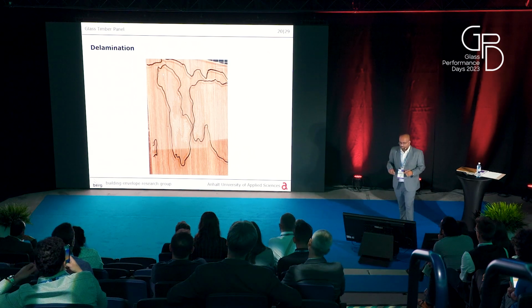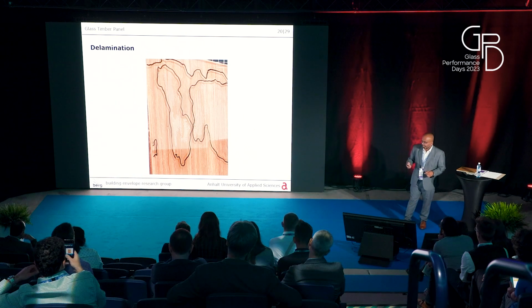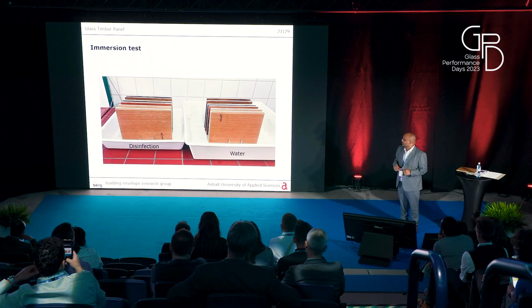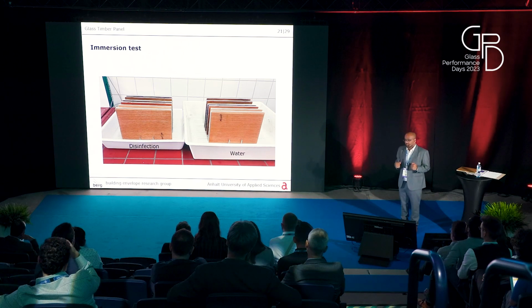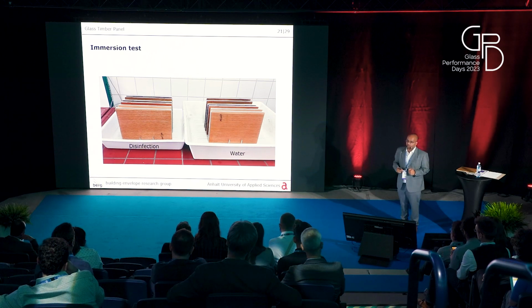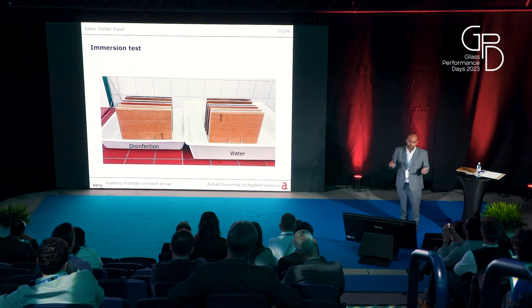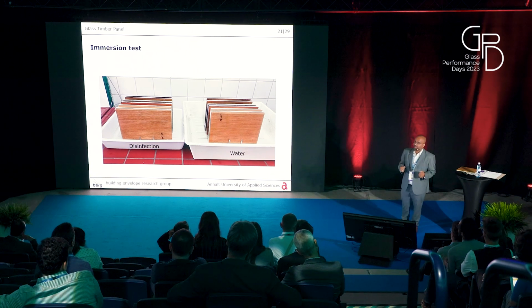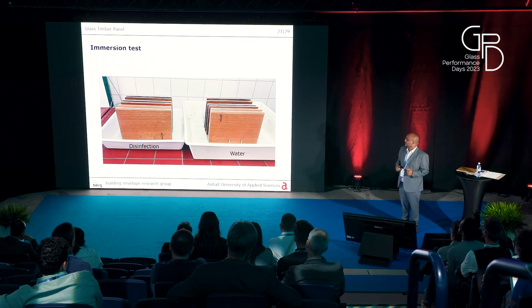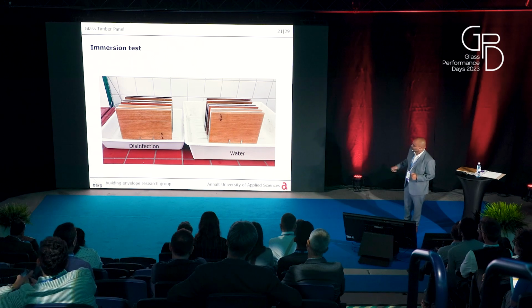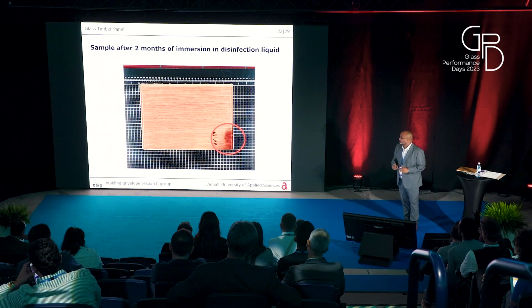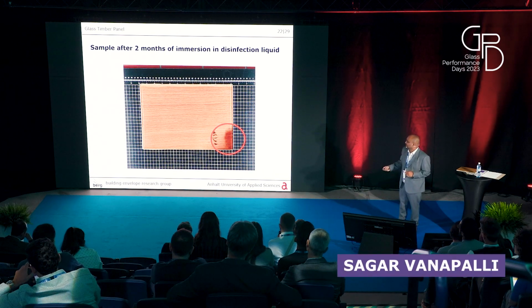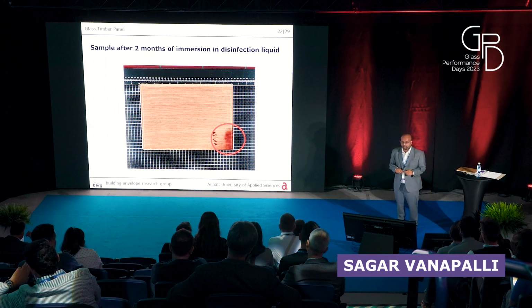Apart from this durability test, we also did an immersion test because we wanted to check if the edges let moisture penetrate or not. Since type 1 and type 2 edges are not treated at all, it is obvious that the moisture would penetrate. So we checked only type 3 samples, each one immersed in disinfectant and water for a period of 2 months, and none of the samples actually delaminated. We see a little bit of deterioration of the wood, but there was no delamination at all.